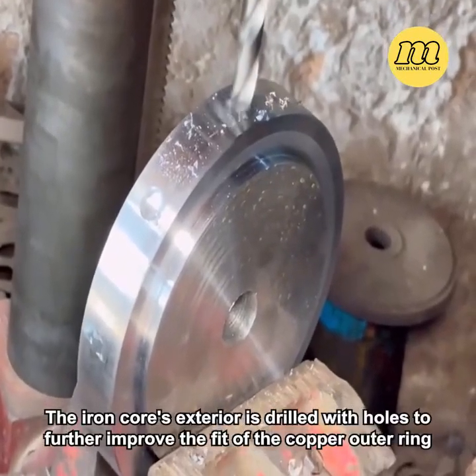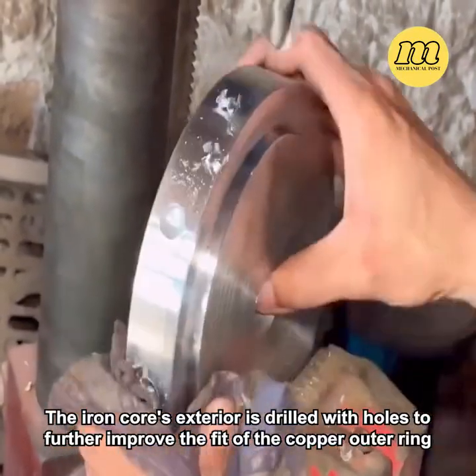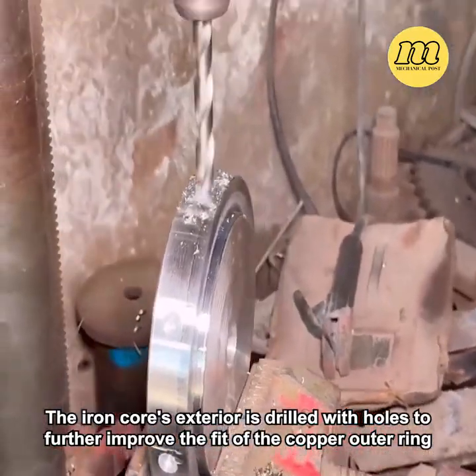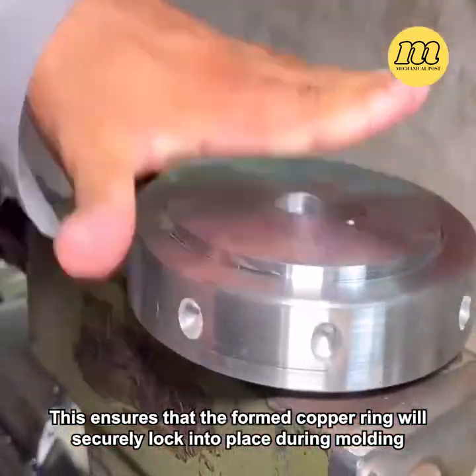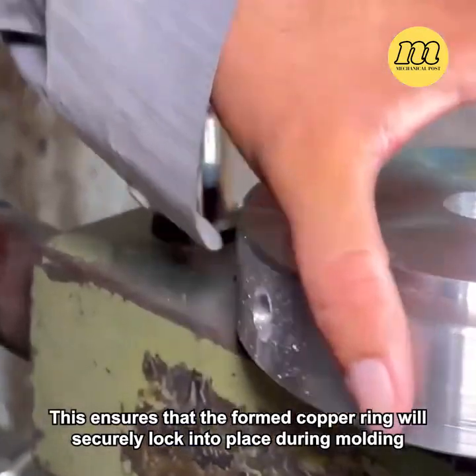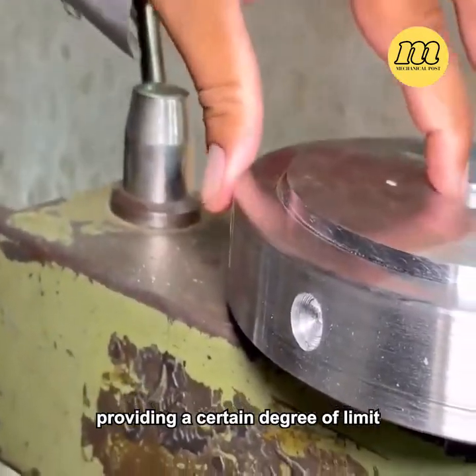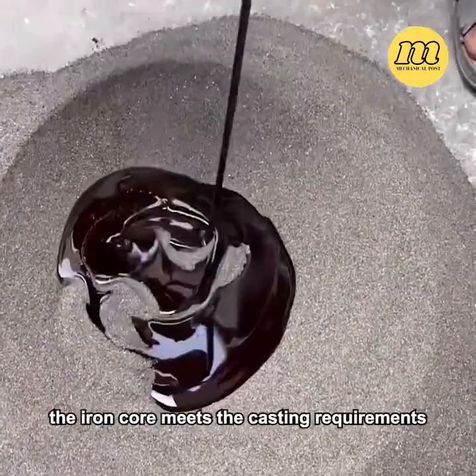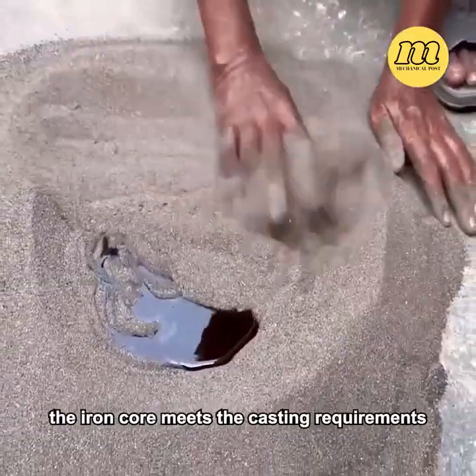The iron core's exterior is drilled with holes to further improve the fit of the copper outer ring. This ensures that the formed copper ring will securely lock into place during molding, providing a certain degree of limit. At this point, the iron core meets the casting requirements.